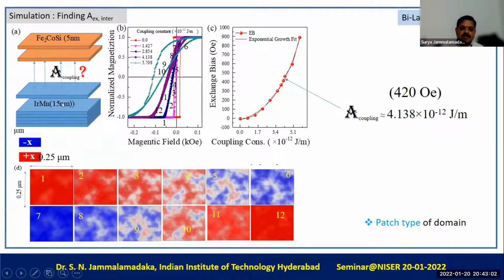Again, at the interface, we also tried to get domain images. We do see patch kind of domains even in the micromagnetic simulation. So these patch kind of domains exactly mimic the kind of patch domains that we have obtained using the magneto-optical Kerr effect, which essentially confirms that there is internal matching between various experiments that we have performed. So this gave us a lot of confidence in our data.